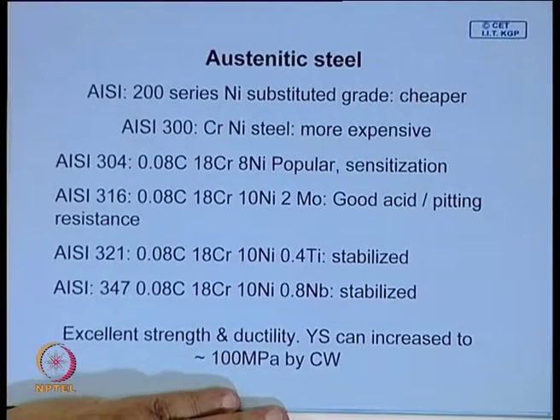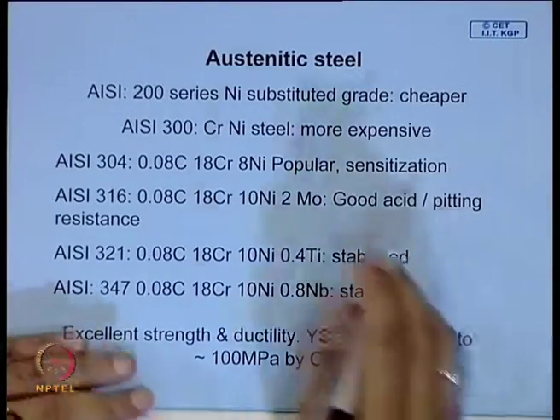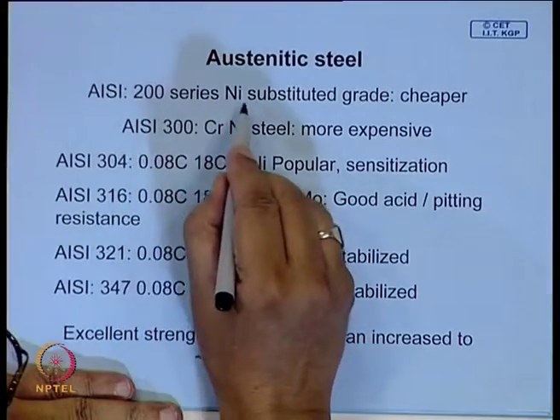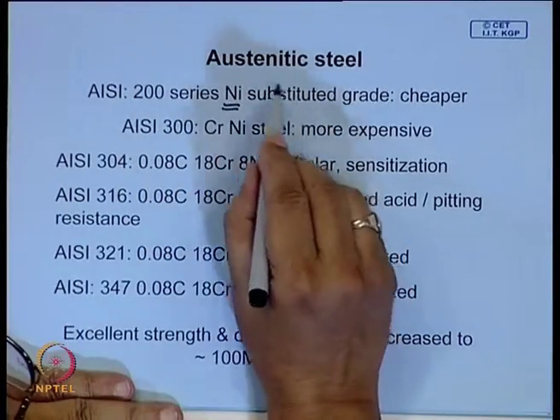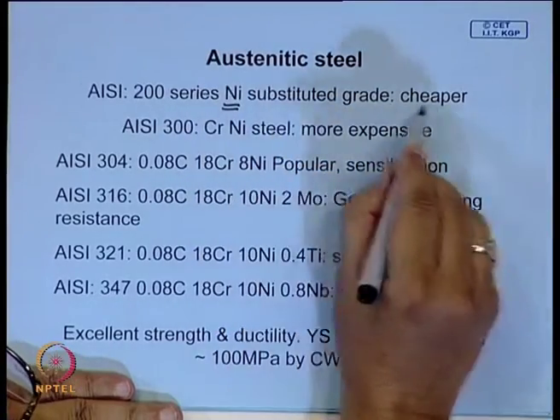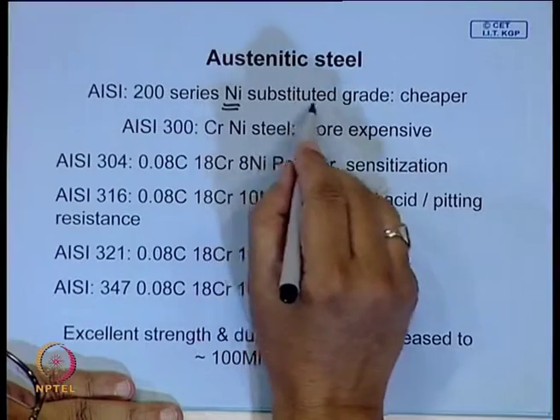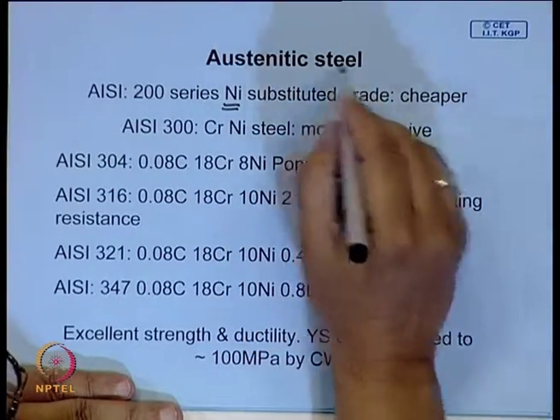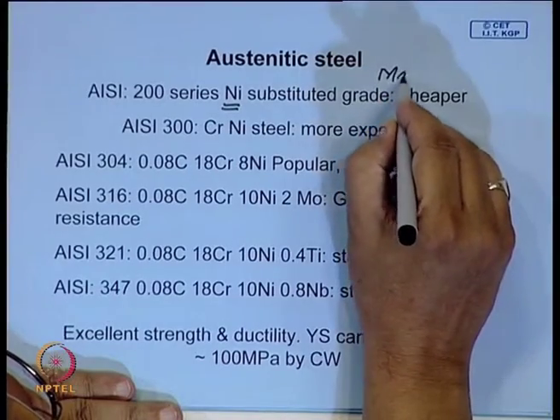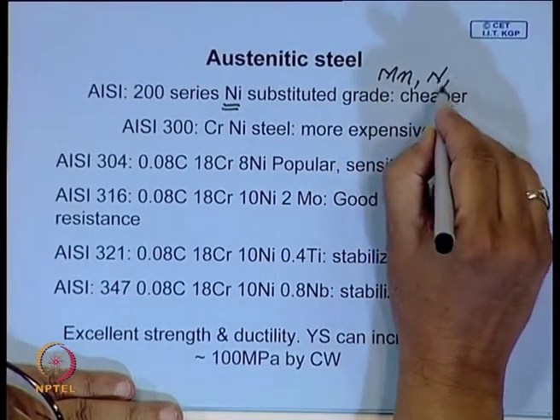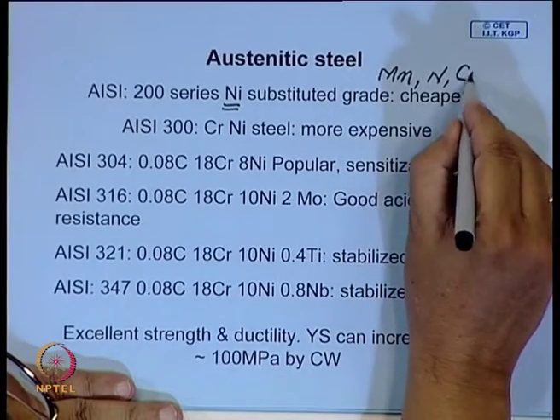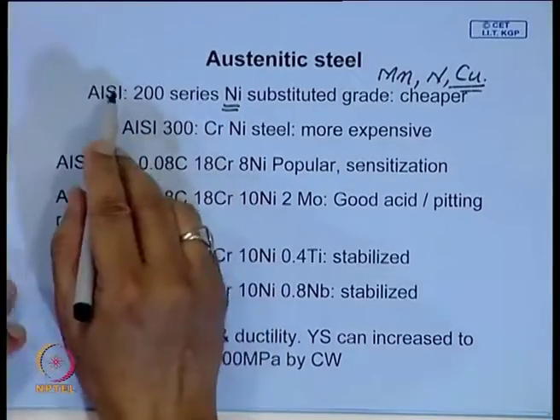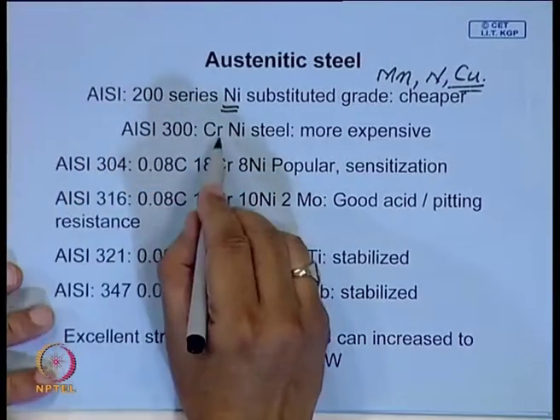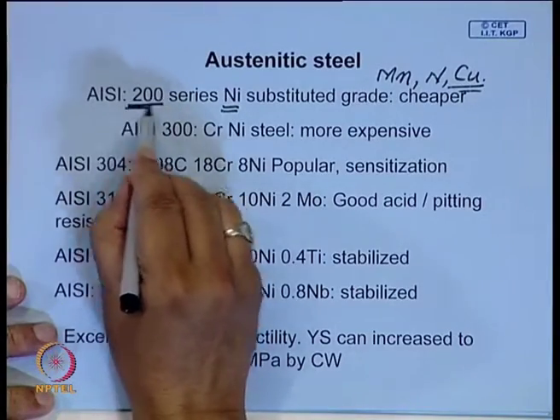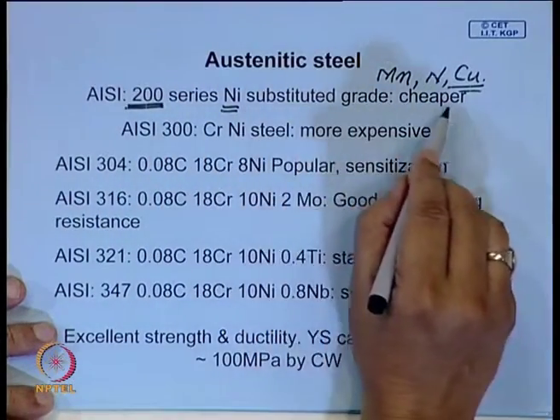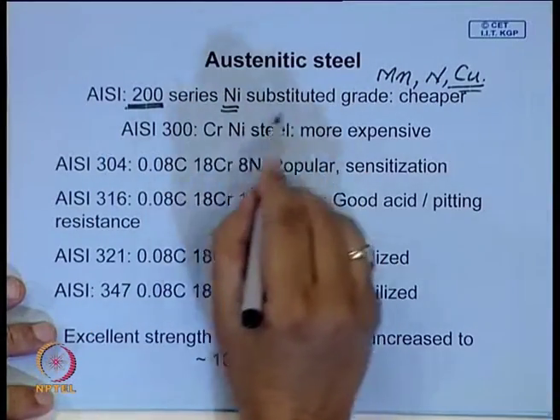Now, we have talked about ferritic and martensitic grades of steel. Now, let us look at some austenitic grades of steels. Nickel is a very expensive alloy element. So, there have been attempts to have austenitic grades which are cheaper, where nickel is substituted either completely or partially, and the common elements used to substitute are primarily manganese, nitrogen, and copper. These are used to stabilize austenite to room temperature. The AISI 200 series is manganese substituted austenitic stainless steel.